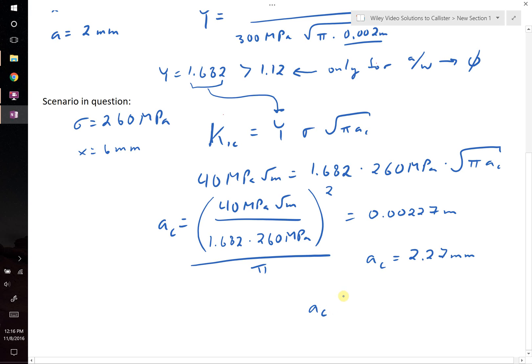This critical crack length is less than our half crack length in this material, 3 mm. Therefore, yes, fracture occurs.